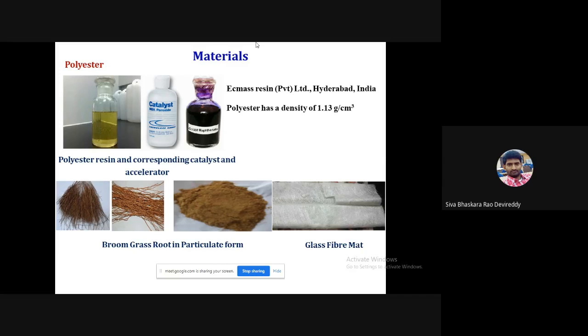The density of this polyester is low compared to the epoxy, that is 1.13 gram per centimeter cube. Broom grass root is selected in particulate form. Initially, the broom grass is collected from local sources, washed with clean water, and made into powder form. In particulate form, we are making this broom grass root.